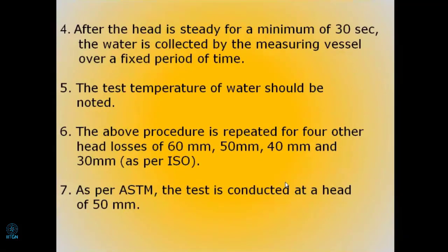After the head becomes steady for a minimum of 30 seconds, water is collected in the measuring jar for a fixed period of time. We have to maintain the test temperature of the water as per the codal provisions, and then repeat the test for 4 other different head losses, which are 60 mm, 50 mm, 40 mm, 30 mm as per ISO. If we are following ASTM, then the test is conducted at a head of 50 mm only. So depending upon the methods or standards, we have to follow the test procedures.